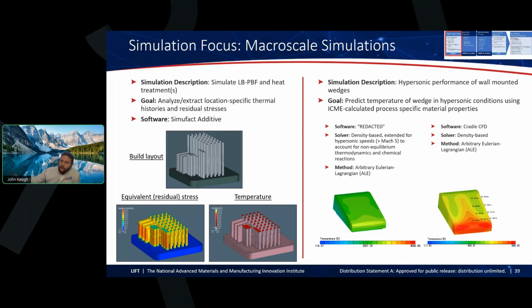And then in the hypersonic test, we're talking about a Mach 5 reacting flow test, similar to what we're setting up at LIFT. We used two different codes to predict the aerothermal environment in the setting of these wall-mounted samples here. And you can see the results are quite different. On the left, the temperatures on the scale are very high. The one on the right is a little bit more realistic. The one on the left is actually a hypersonic code. We're redacting it just because we've worked with them to solve some of the issues there. But not all codes are created equal. All models are wrong, some are useful, and so you have to be careful about that.